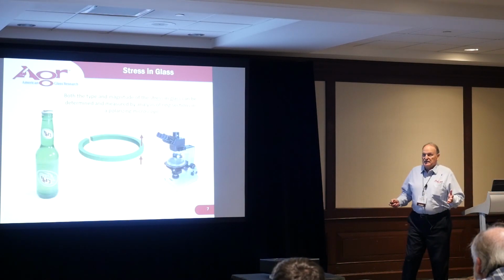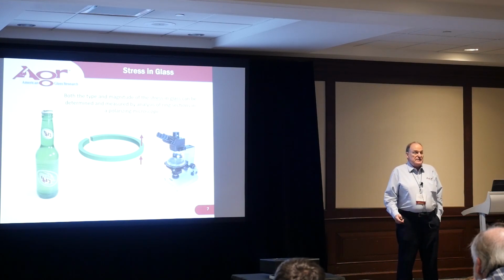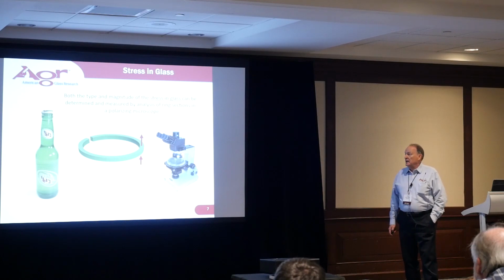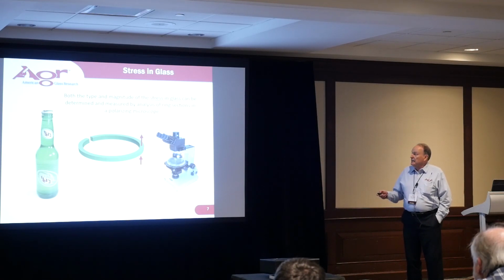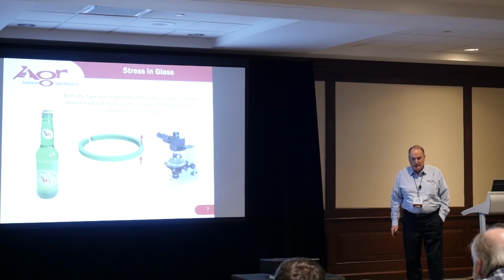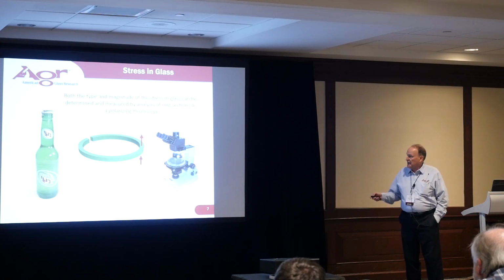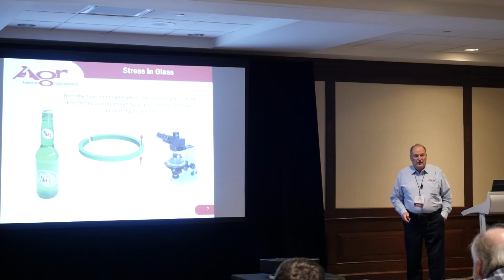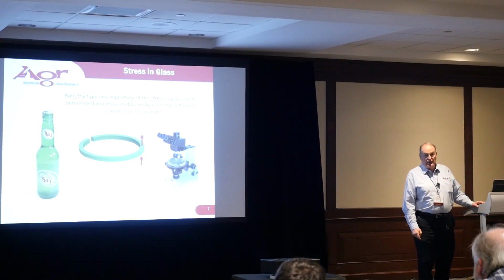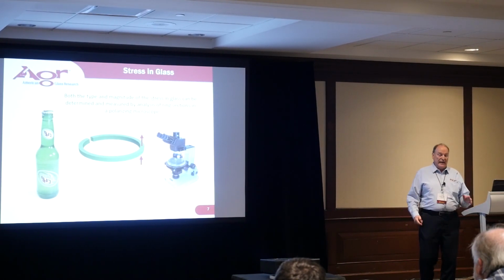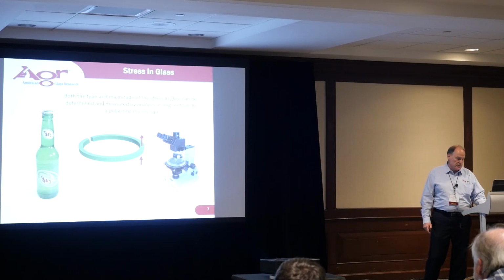Now, the stresses in the glass created by these ceramic labels are easy to identify and easy to measure. For example, if we have this bottle over here on the left and we are interested in knowing how much stress is created by this red or white label, we can cut a ring section from that section of the bottle, depicted here, put that in a polarizing microscope, pass polarized light up through the thickness of the ring section, and we can assess the type of stress that's in the glass, and we can measure the magnitude of that stress with suitable compensators.